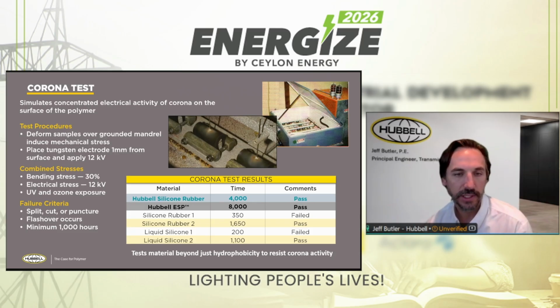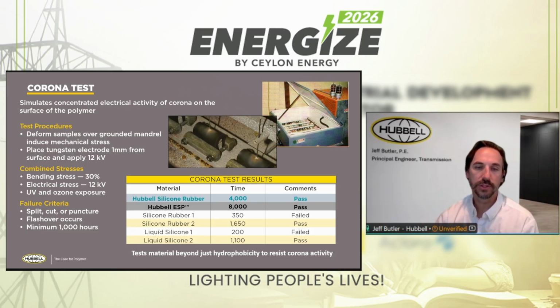Again, it was interesting to see the difference in the performance of what should have been similar materials. Between silicone rubber 1 and 2, liquid silicone 1 and 2, there were dramatically different results in the behavior of the polymers. Now you may be saying, maybe there was a bad sample or it was mixed improperly, but this test was done with multiple plaques. 5 samples were taken, and it was averaged across multiple samples of the rubber in order to determine these results.